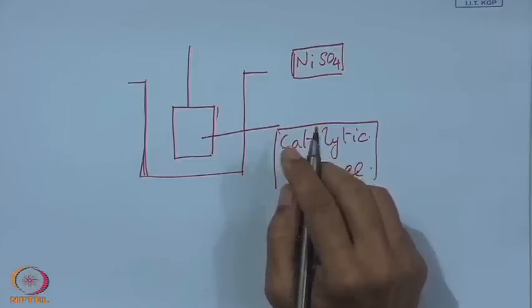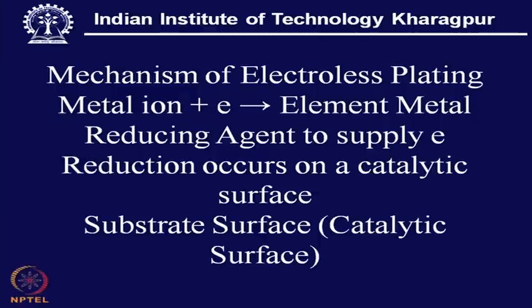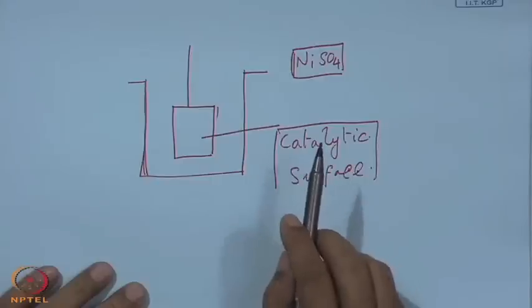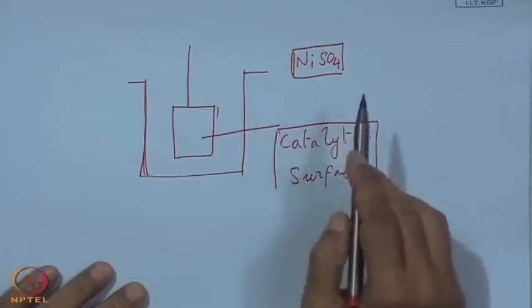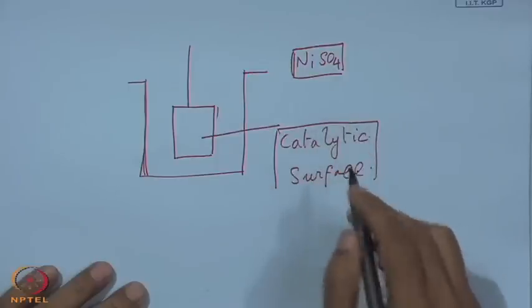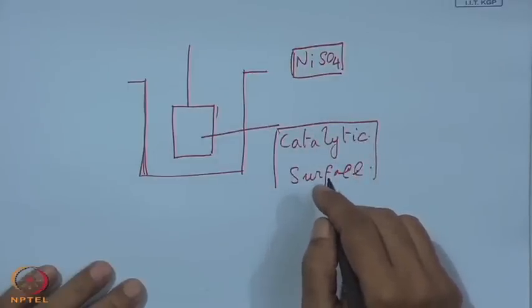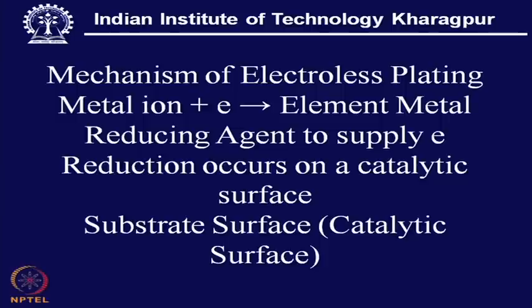So, here what we find in the mechanism of electroless plating is the generation of metal ions, and this metal ion will be neutralized by electrons. Who will supply this electron? That means there is one reducing agent, and this hypophosphite is going to release this electron, and by the addition of this electron on the surface, we get the metal element. So, metal ion plus electron, this is really reduced by the electron, and we get this metal element.